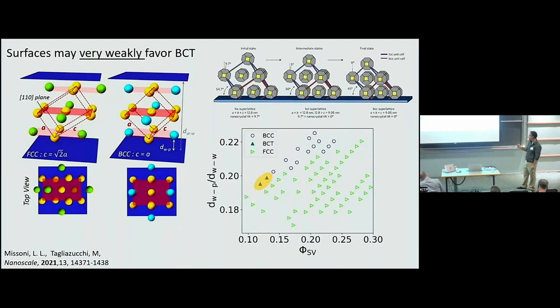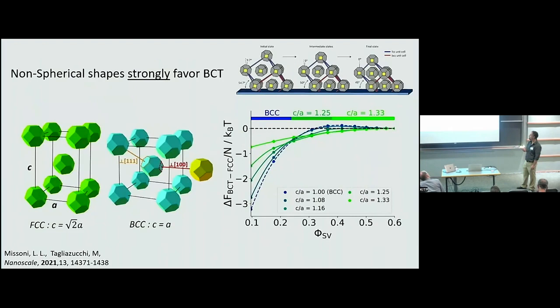So we believe this is not the right explanation, so we looked at the problem of the non-spherical shapes. The nanoparticles used in this experiment had a cuboctahedral shape, similar to a truncated octahedron. And what we did is we just took the orientation of the particles from the experiment, because it was difficult to explore all the configuration space. And again, we looked at the free energy of the different potential structures, and we got a lot of BCT phases in that case.